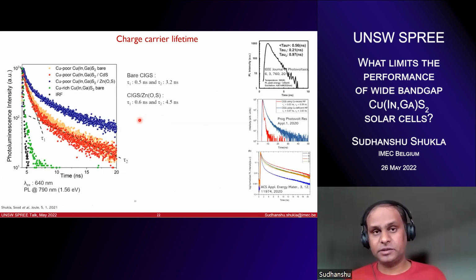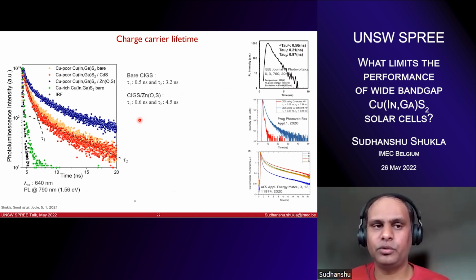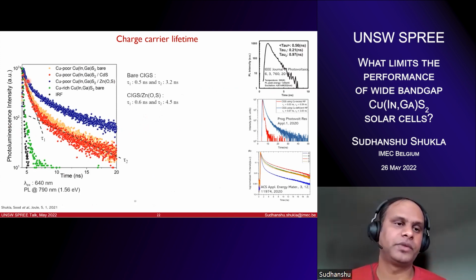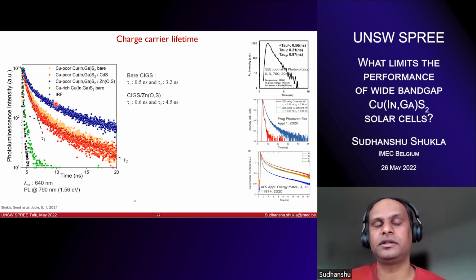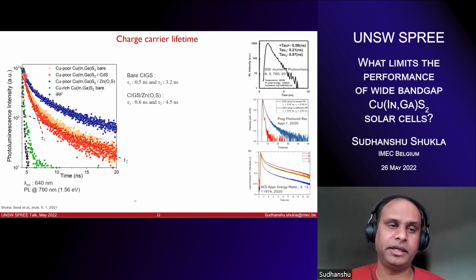And as expected, we were anticipating some improvement in the lifetime. So what you see is that you have a copper rich absorber, which has a very bad lifetime, which is this green decay curve. If you look at the copper poor absorber, it has a higher lifetime as compared to copper rich. But if you put zinc oxysulfide on top of it, it improves even more. And if I then depict it mathematically with these two different decay regimes, tau 1 and tau 2, I get these numbers, 0.6 nanoseconds and 4.5 nanoseconds. This is what you see in the literature, for example.